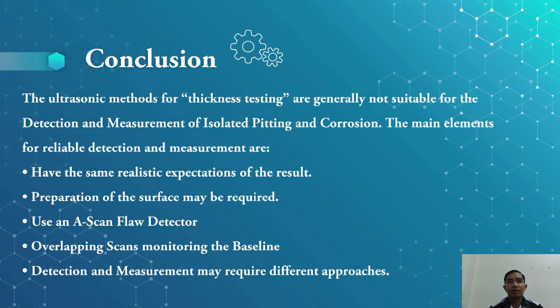So the last slide is the conclusion. We can conclude about the case study. The ultrasonic method for thickness testing is generally not suitable for the detection and measurement of isolated pitting and corrosion. The main elements for reliable detection and measurement are: number 1, have realistic expectations of the result. Number 2, preparation of the surface may be required. Next, use an A-scan flaw detector, then overlapping scan monitoring of the baseline, and last, detection and measurement may require different approaches.